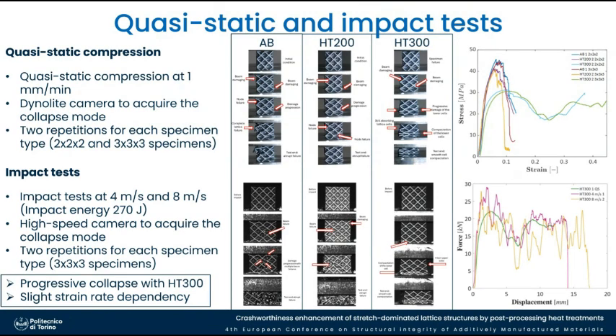heat-treated specimens showed a very progressive collapse, even if we are in this dynamic case. And also, if you look here, I'm reporting the results of the 300 degrees. We have the quasi-static one here in green, and then the other test, the impact test, in the other color. And you see that there is an increase of the maximum force, basically. So this means that there is a slight strain rate dependency of the material.